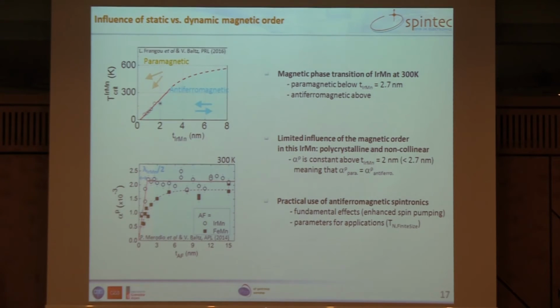By knowing this effective spin-spin correlation length, and by using the same model, it's possible to extrapolate to thicker layers, and then we can plot the full phase diagram for iridium manganese. So critical temperature as a function of thickness. On the left-hand side, we are paramagnetic. On the right-hand side, we are antiferromagnetic. And what's interesting here is the data point at room temperature, because the thickness threshold for the magnetic phase transition at room temperature is around, well, say 3 nanometers.